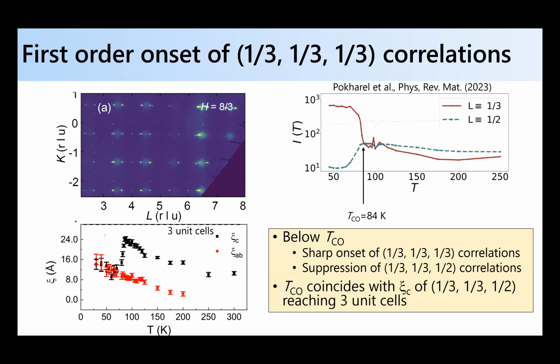And one can look at this a bit more. So this is looking at a third plane. You can see these sharp Bragg peaks, right? These are for the long-range charge order. You can see this diffuse scattering cutting through. That's just from these short-range correlations of a third, a half wave vectors. We can watch the correlation length diverge along the c-axis, along this diffuse scattering, a third, a half. It diverges, it hits about 3 unit cells, and then it crashes down, and you have this sharp onset of long-range charge order. So it's kind of an interesting example of a one-dimensional instability along the c-axis that is frustrated from forming, where the frustration is mediated via the vanadium-based network.